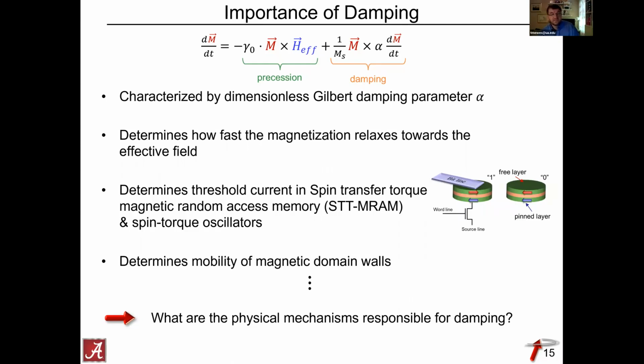It first of all determines how fast the magnetization relaxes towards the effective field, but it also determines the threshold current in spin transfer torque MRAM or in spin torque oscillators. It also determines the mobility of magnetic domain walls. Which leads us to the question: what are the physical mechanisms that are responsible for the damping?